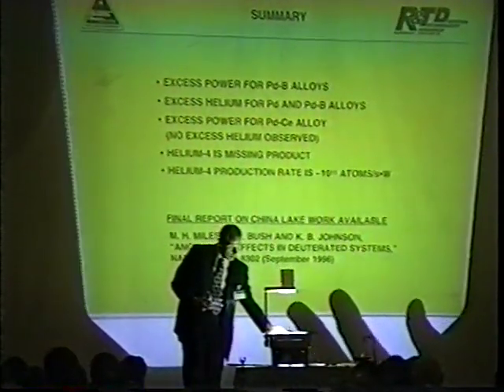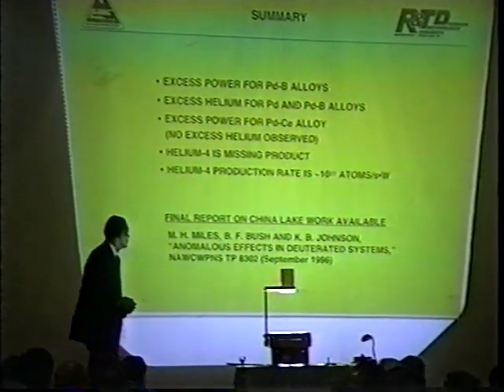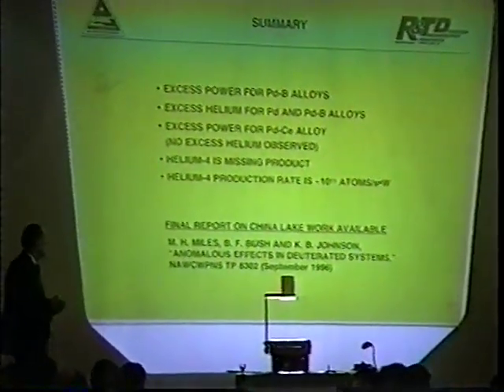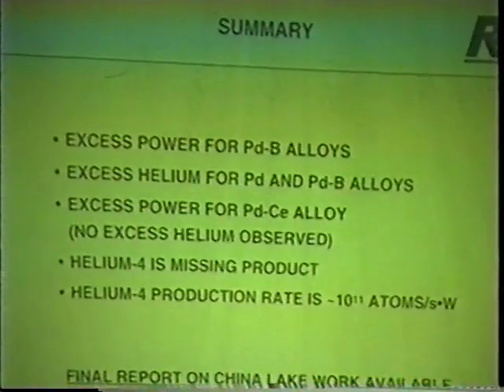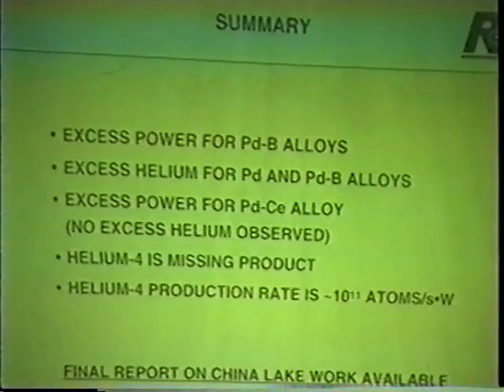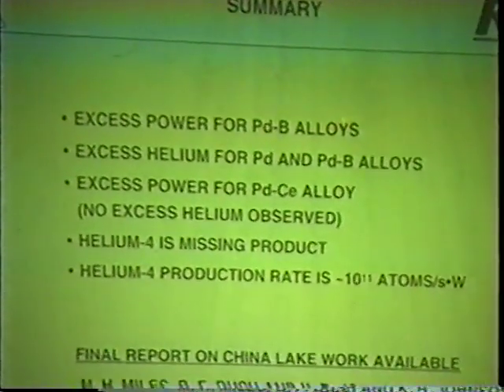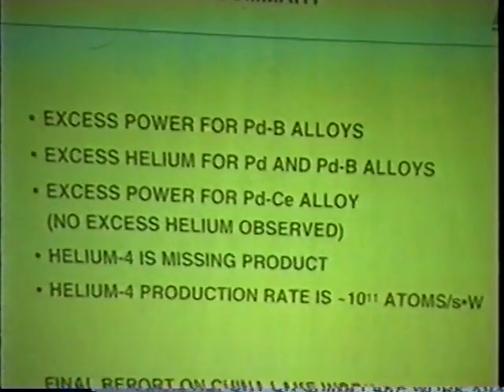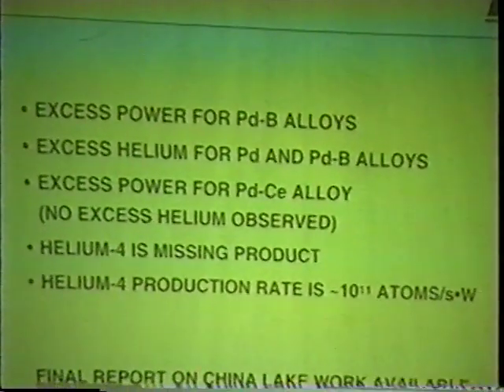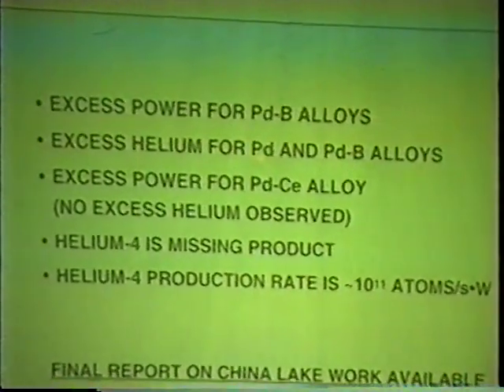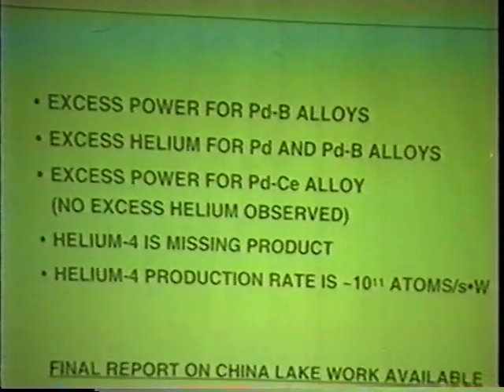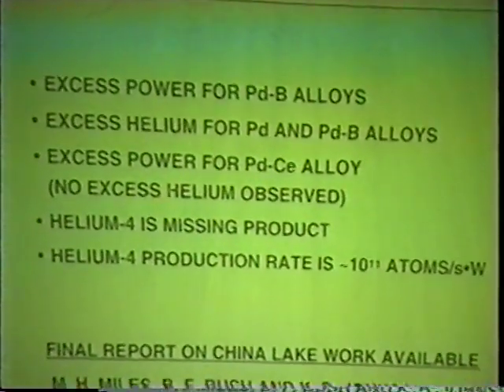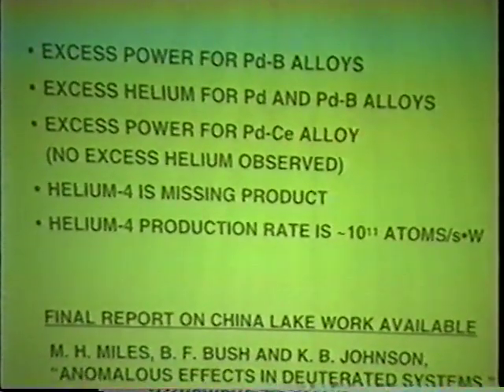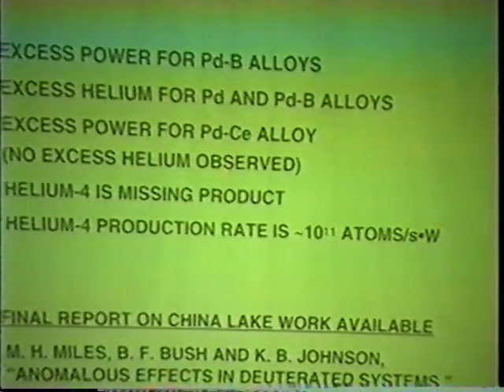In summary, we found excess heat for palladium boron alloys, a high success ratio. 7 out of 8 studies gave excess heat when we had boron present in the alloy. We found excess helium for palladium and palladium boron alloys. We did not find helium when we did the palladium cerium alloy. We found excess heat, but we did not get excess helium.